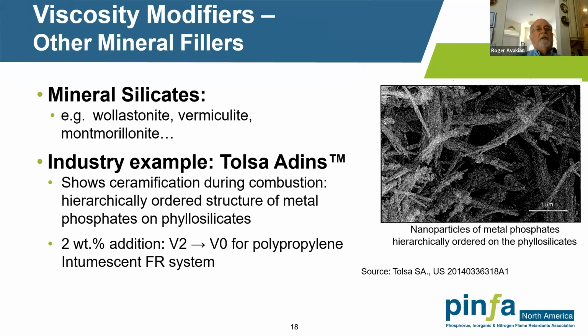So here's a ramification of this type of technology, again using mineral silicates, other ones like wollastonite, vermiculite, and montmorillonite, which is the basis for nanoclays. But what I'd like to point out here is a treatment for a mineral filler. This is from Tolsa, and it's called Adins, a trademarked material. If you go read their patents, they typically take this fibrous type of mineral and impregnate it with some metal phosphates, etc., to enhance charability and ceramification, or making the material turn more into a ceramic during combustion. So at those temperatures, the material tends to sinter together and turn into a ceramic.